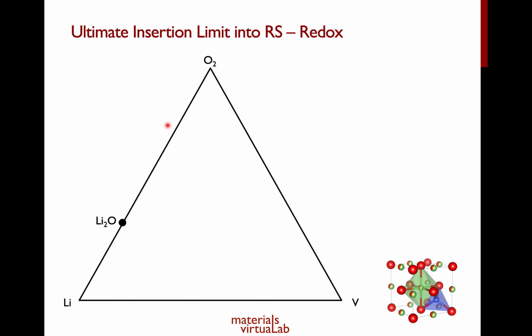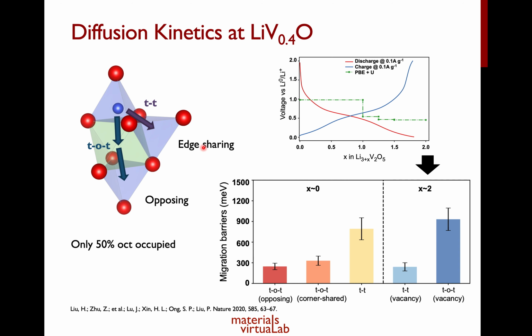Now, those results essentially show that we have very low barrier lithium migration, at least both at the start of charge and discharge for this disordered rock salt Li3V2O5 anode. And that explains why we are able to achieve such high rate capabilities in the disordered rock salt.